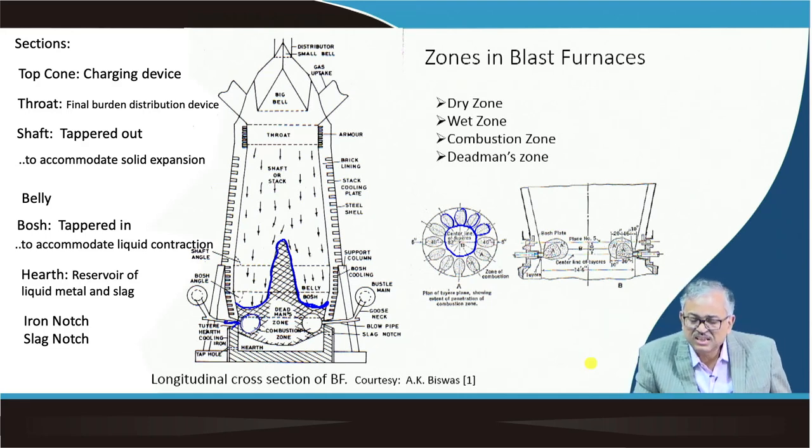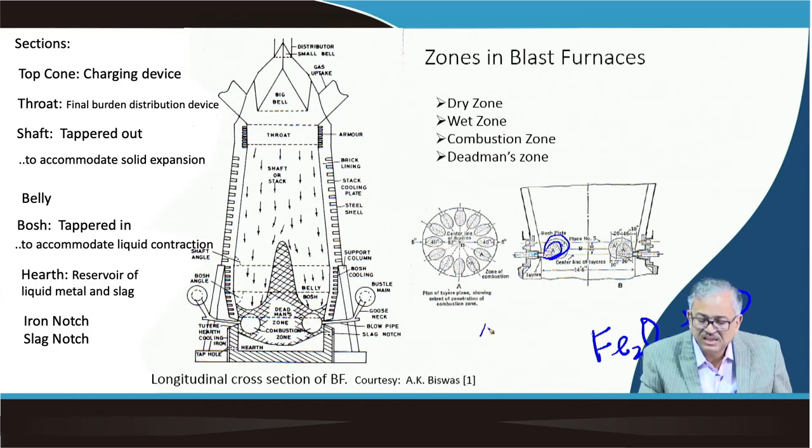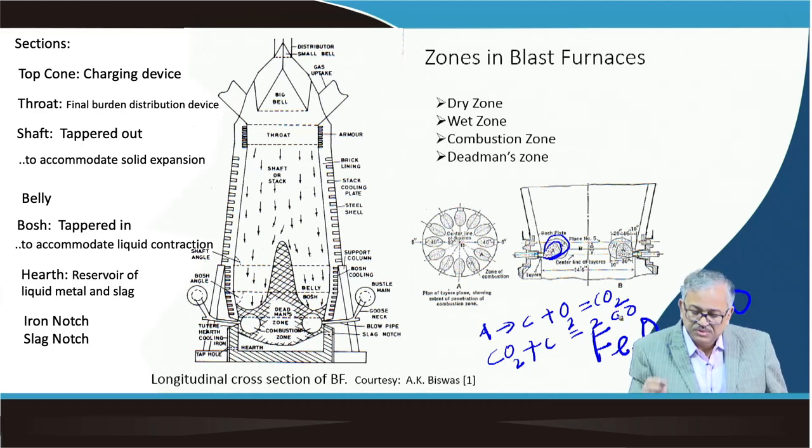And in the combustion zone, there are two areas you can find, A and A prime. There are two regions in the combustion zone. First is the A region. Here, when air comes, it directly reacts with the oxygen, forming CO2. And then when the CO2 crosses this envelope and comes to the next envelope, this CO2 is not stable. In the presence of carbon, it forms CO gas.